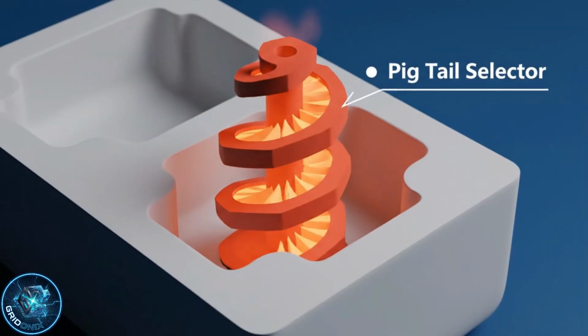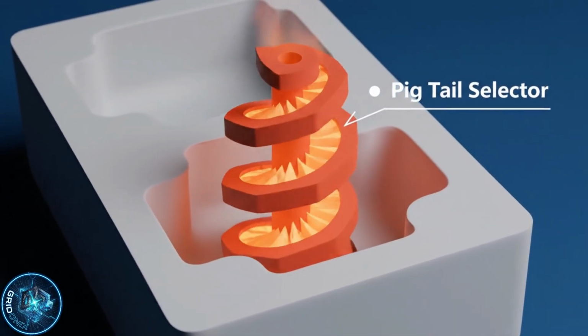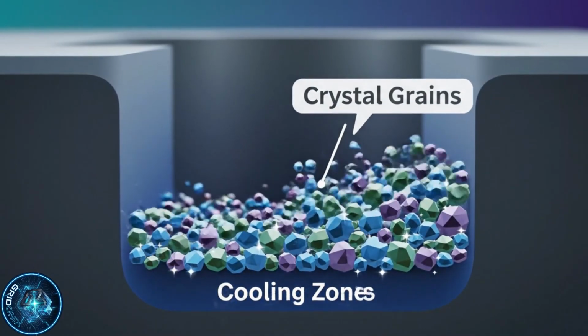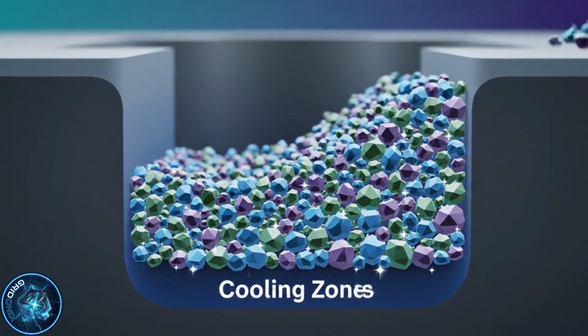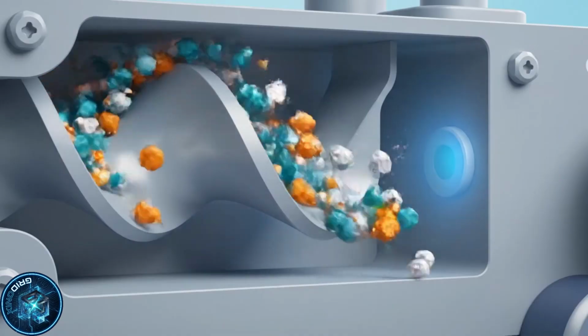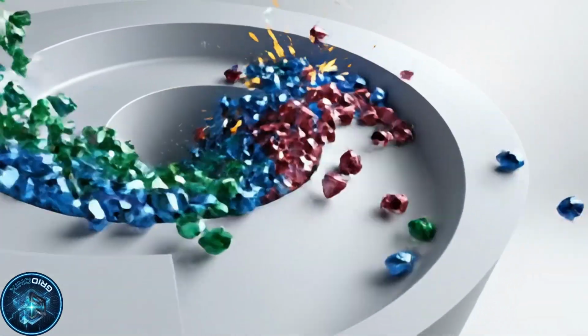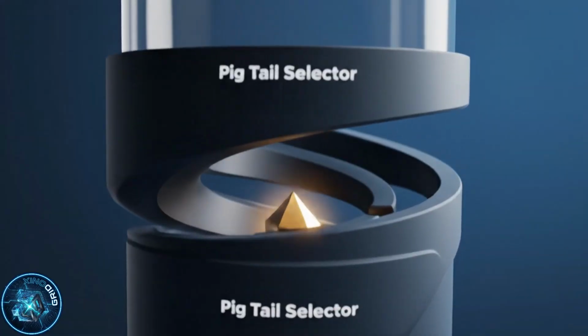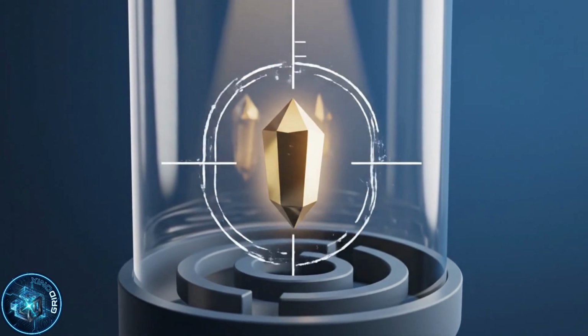Then, the mold is slowly withdrawn from the furnace, millimeter by millimeter. At the bottom of the mold, there is a geometric filter. It is a corkscrew shape, often called a Pig Tail Selector. As the metal at the bottom begins to cool and solidify, many crystal grains start to form and race upwards. They enter the helix of the pigtail. Because of the spiral shape, the grains collide with the walls of the passage and are blocked. Only one single grain, the one perfectly oriented with the vertical axis, manages to survive the spiral maze.